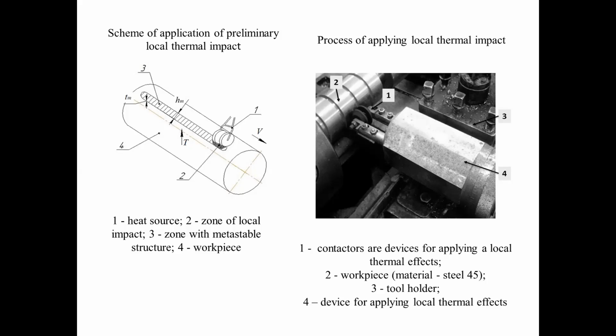The subsequent machining step with the set rotation speed of the workpiece N and the feeding of the tool S provides an intersection at the point T of the cutting insert with the trajectory of the metastable structure. The local zone with distorted crystal lattice and mechanical properties different from the main metal volume causes an instant change in the stress-strain state in the chip formation zone.